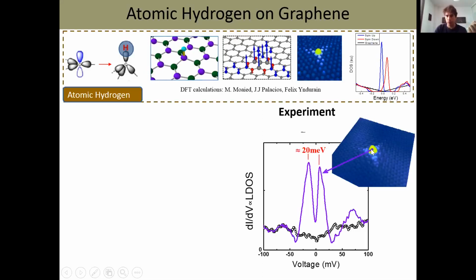And now when we do STS experiments on top of the hydrogen atom, we observe the two peaks in the density of states, one below the Fermi energy, one above the Fermi energy, and we ascribe these two peaks to the spin polarized peaks predicted by theory. You can see here that the spin split, the peak separation, is around 20 millielectron volts. So let me explain a bit which is the physical origin of this splitting, because probably the energy scale is not what you are used to.